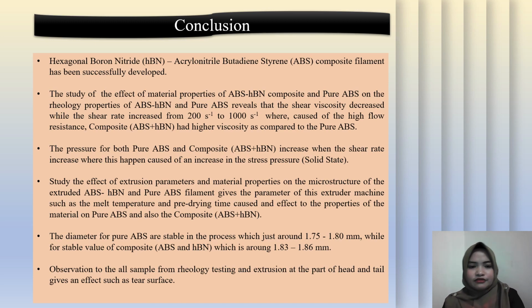Because of the high flow resistance, composite ABS HBN had higher viscosity compared to pure ABS. The pressure for both pure ABS and composite ABS HBN increases when the shear rate increases, which happens because of the increase in stress pressure in the solid state. The study of the effect of extrusion shows that the parameters of the extruder machine, such as melt temperature and pre-drying time, affect the properties of the material for pure ABS and composite ABS HBN. The diameter for pure ABS is stable in the process at around 1.75 to 1.80 mm, while the stable value for composite is around 1.83 to 1.86 mm.